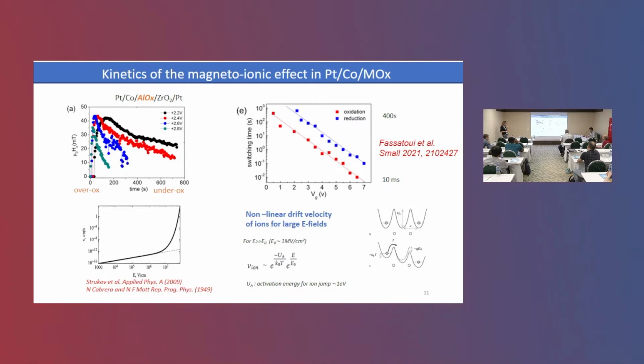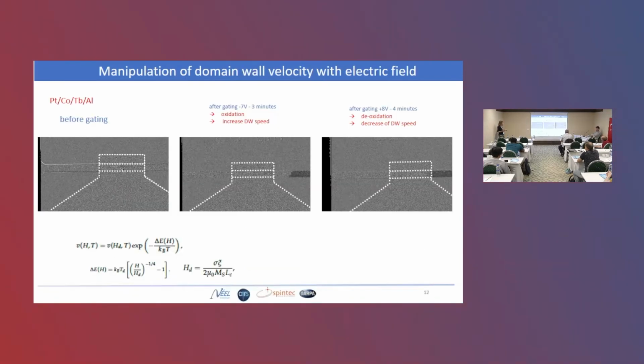And what they show is a theoretical model that says that beyond a certain threshold electric field, the drift velocity of ions would change exponentially with the voltage. From this expression, you can extract the activation barrier for ions to jump from one valence state, or vacancy state, to another. And from this slope, we actually get a value for this energy barrier of about 1 electron volt, which is consistent with what is found in the literature.